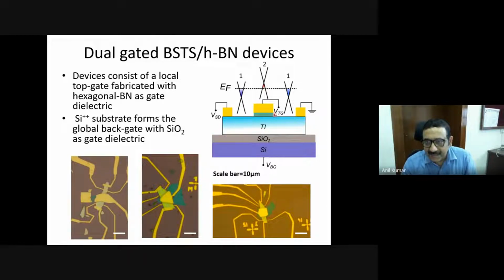Similarly, I have a top gate, and if I apply a voltage in this top gate, I can make this local region P-type or N-type. So this is the idea. You apply the gate voltage in such a way that if you bring the Fermi level below the charge neutrality point, you will get a p-type region here. If the Fermi level is above the charge neutrality point, then it's an n-type region.